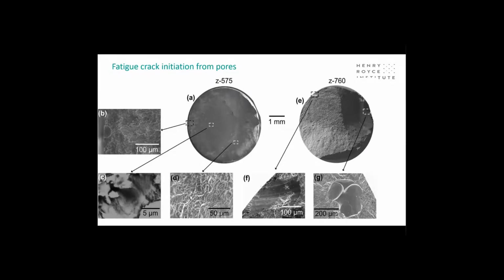Of course, these defects can be critical often in terms of fatigue, and generally the microstructure, the grain structure, which is anisotropic, will affect the fatigue life. But if we don't get rid of them, the majority of the defects can play a dominant role in shortening the life of additively manufactured parts. Often those defects occur, as you can see on the left, near the surface, and fatigue cracks will grow from near surface defects. But in addition, you also find other defects deeper inside additively manufactured parts, as you can see here.